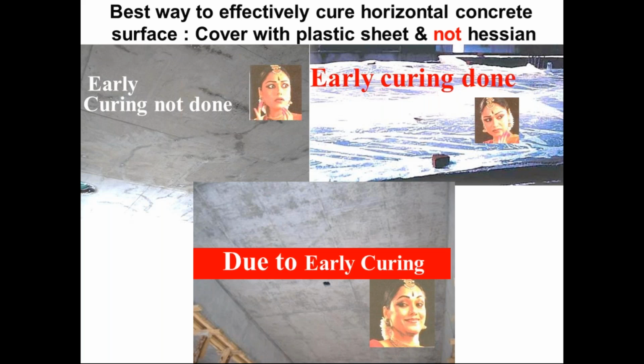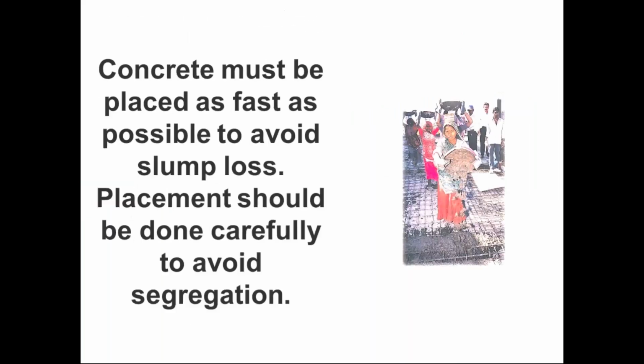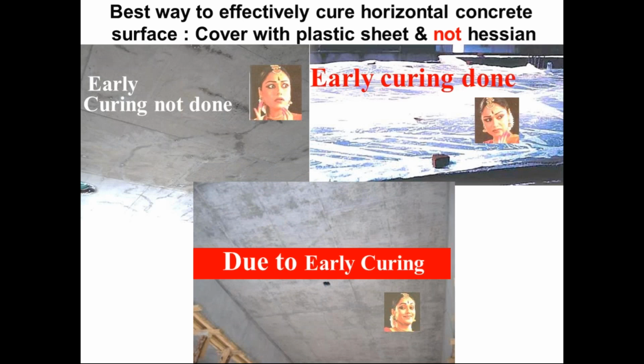So the customer complained, and we went there with this plastic sheet and demonstrated to the customer. This next slab which was cast, you can see there is about 5 to 6 inches of water ponded on the surface of this concrete, and no through cracks appear, or it almost eliminated this plastic shrinkage crack totally.